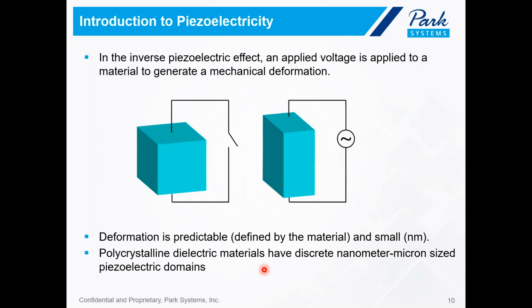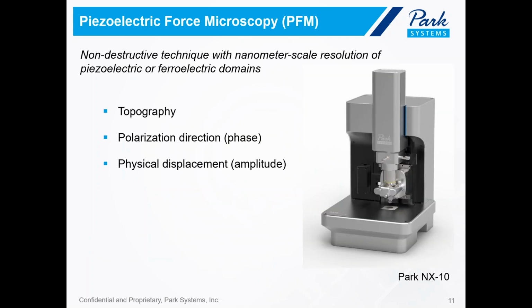And that brings us to atomic force microscopy, AFM, and piezoelectric force microscopy, PFM. PFM is really a non-destructive technique that has nanometer scale resolution, and it allows us to characterize these piezoelectric and ferroelectric domains at the nanometer length scale without sacrificing your sample, without putting any damage to your sample, ideally.